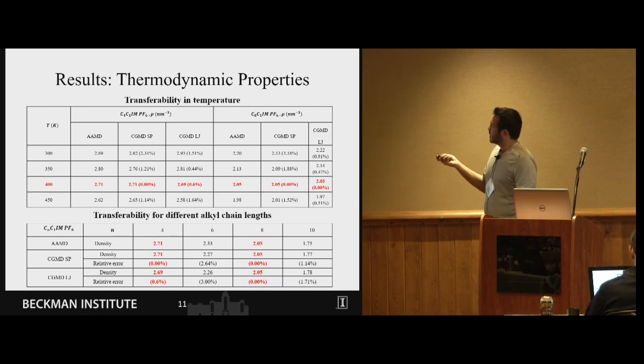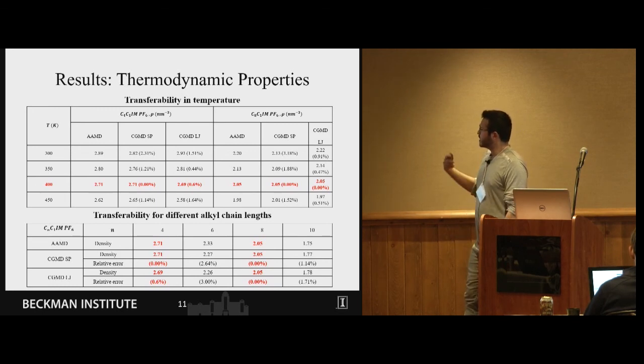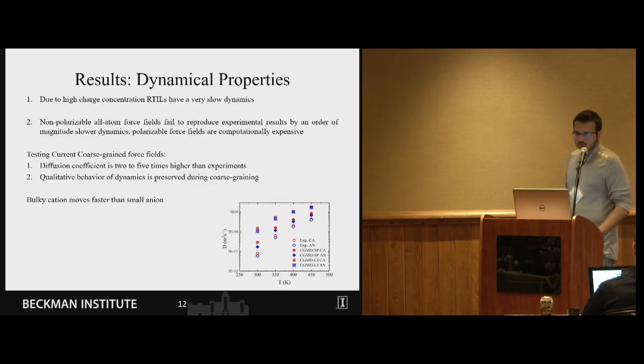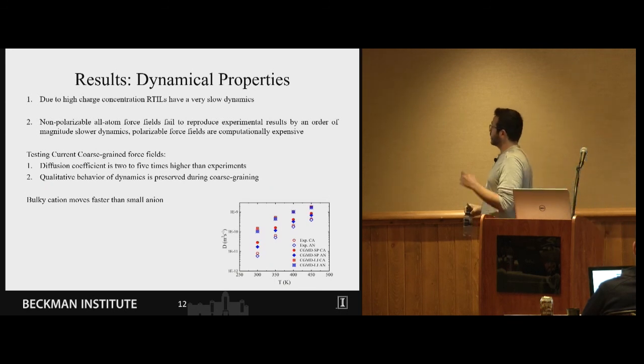I'm showing the reference system with red color. Then we studied the transferability for different alkyl chain lengths. We only considered two references C4 and C8, we wanted to see how our force field is transferable to other alkyl chain lengths. So we studied two other alkyl chain lengths including n equals to 6 and n equals to 10 and we saw that again density is reproducible with a good error of maximum three percent.